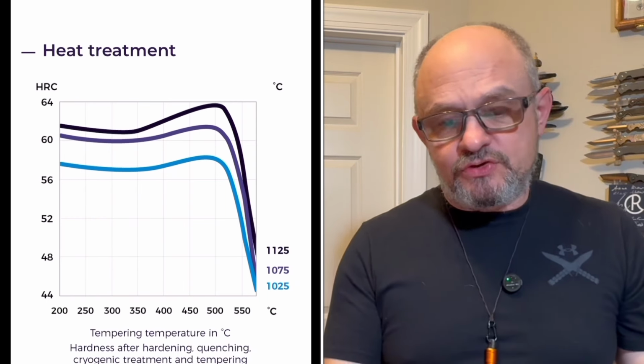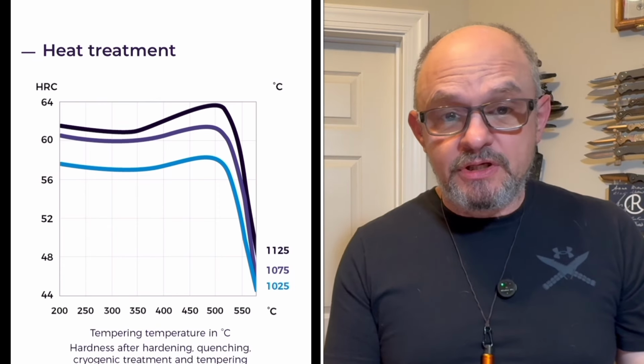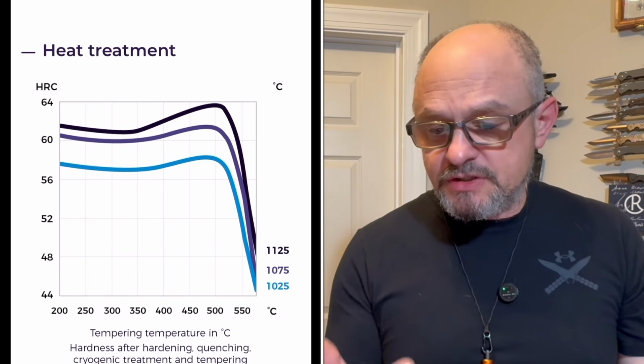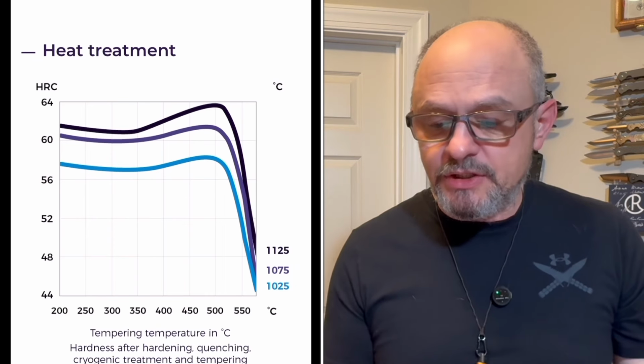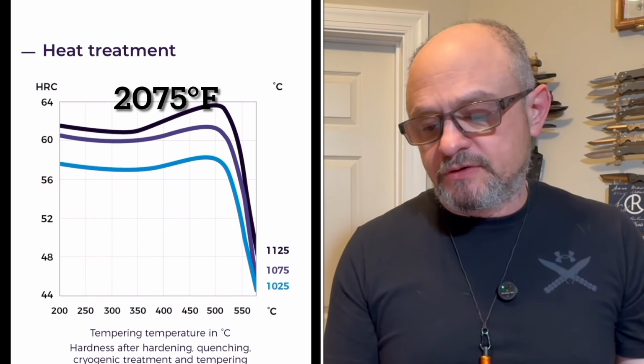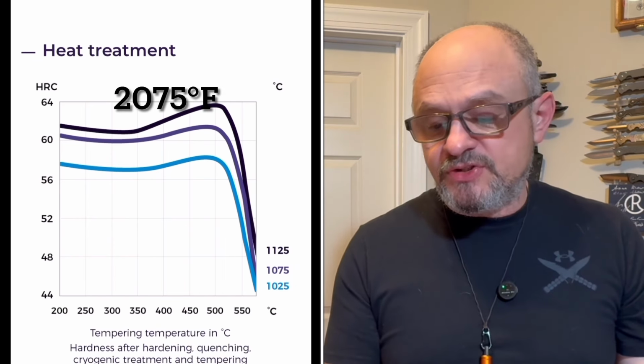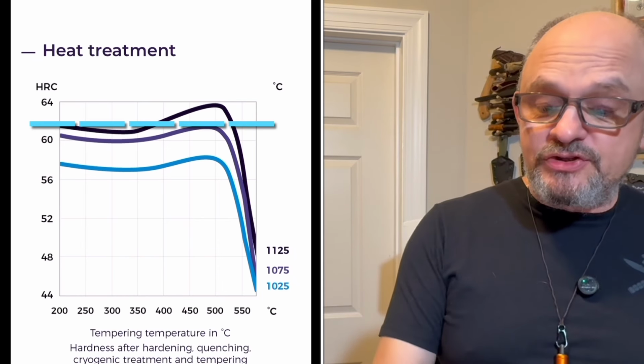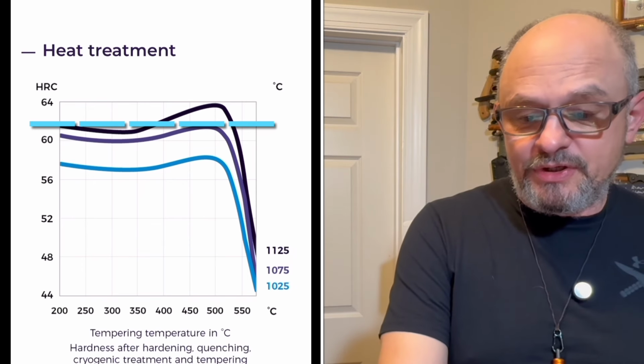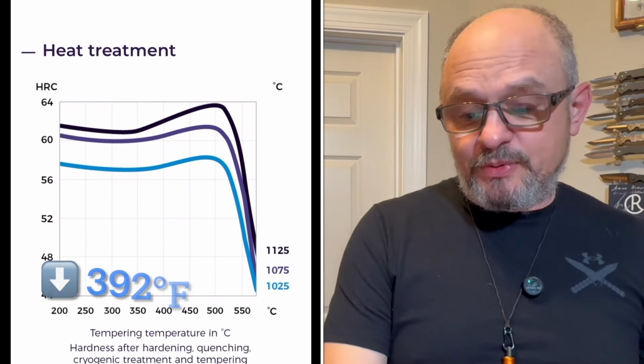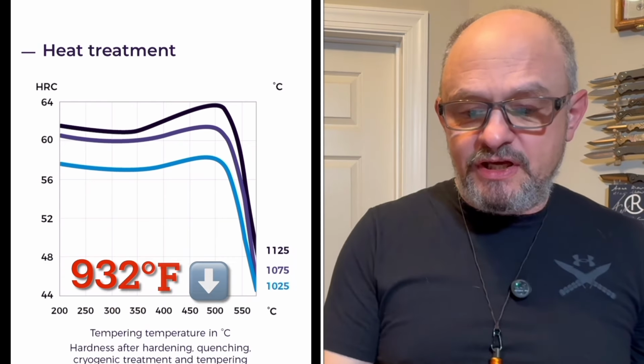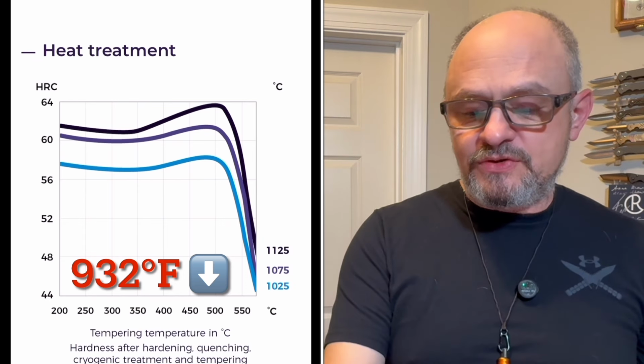So if we were to assume that Mr. Shirogorov heat treats his steels to the maximum edge retention, he would go with the first line on this chart, which means he would austenitize it to 1125 centigrade. And as you can see, it is incredibly stable during the tempering process. You can temper at 200 all the way up to 500 with almost no deviation in hardness. So if you do it at 200, you can achieve